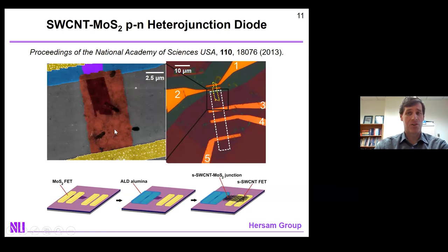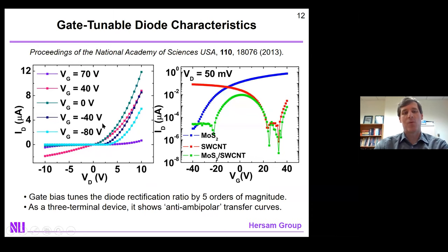And what you see in the two-terminal response is what you'd expect for a P-N junction diode, and that is a rectifying IV curve, as you see in the light-blue plot here. This, of course, is not new. Rectifying diode characteristics have been around since the 1930s. But what was interesting about this device is that, because the materials are atomically thin and we have incomplete screening of vertically applied electric fields, we can now gate this two-terminal device and make it a three-terminal device.